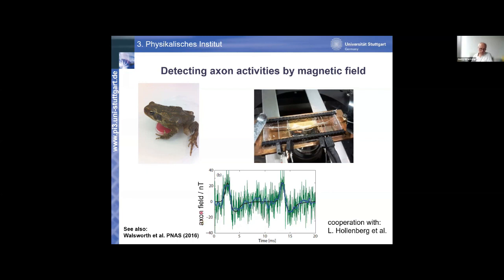So you see here the axon magnetic field. This is actually a misprint. It's not nanotesla, but picotesla. The magnetic field amplitude we measure here is up to 20 picotesla. And the temporal response, the signal shape you see here, is very typical for action potentials, which have this positive and negative sign, which is an indication of the physiological process underlying these action potentials.